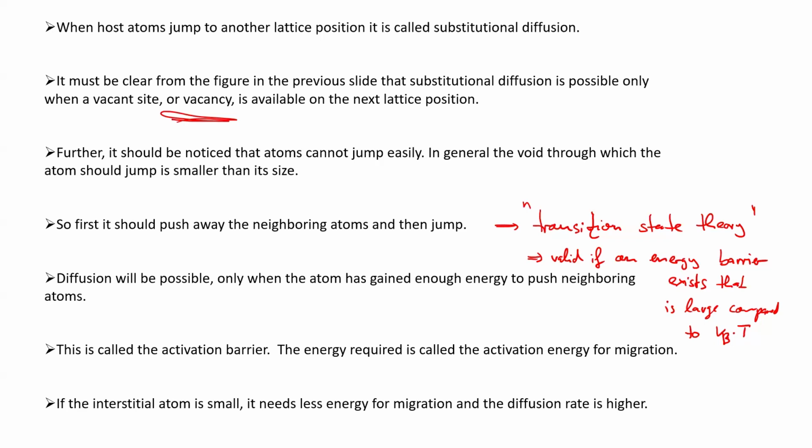If an energy barrier for any process is small compared to kBT, the statistics of describing any type of reaction occurring means that you are in the fluctuation regime, meaning that the reaction can take place any time. Any oscillation, any excursion of the system might actually go to the new state. In this case, diffusion, it means the hop, the jump can take place.